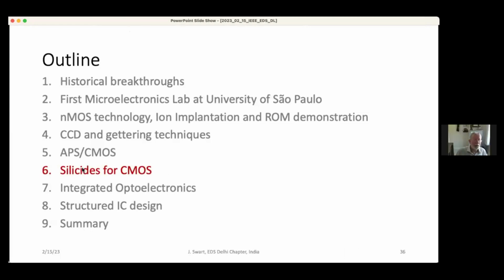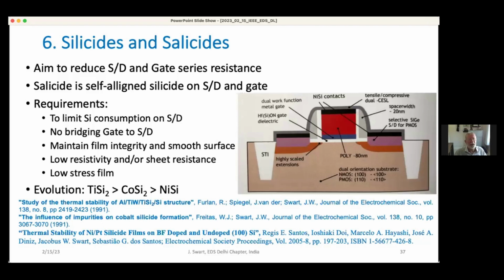We also worked, I had a team working on silicides for a long time. Silicides are needed for CMOS and other applications, and are aimed at reducing source, drain and gate series resistance. So you shunt your silicide on top of the source and drain and on top of the gate in order to reduce the sheet resistance and contact resistance. But there are requirements to limit silicon consumption. You also need to avoid shorting between the gate and the source and drain, because the